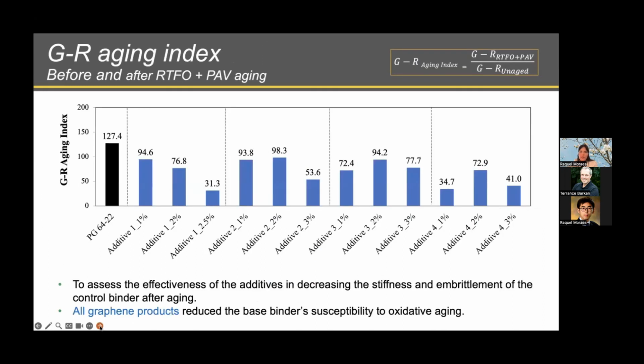By utilizing also the Glover-Rowe parameter, an aging index was calculated, considering the Glover-Rowe after short and long term, and the Glover-Rowe of the original material before being subjected to any type of aging. And here we have the Glover-Rowe aging index of the base binder in black and in blue for the graphene-modified binders. Usually, if the aging index is lower than the control, than this black column, it means that the tendency of these